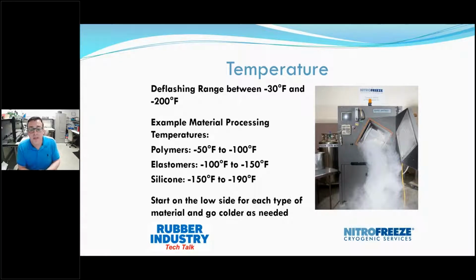Next, we have elastomers. We run those between -100 degrees Fahrenheit and -150 degrees Fahrenheit. And then silicone is the material that we process at the lowest of temperatures with the deflashing process. That range is -150 degrees Fahrenheit to -190 degrees Fahrenheit. And again, you want to start on the low side.